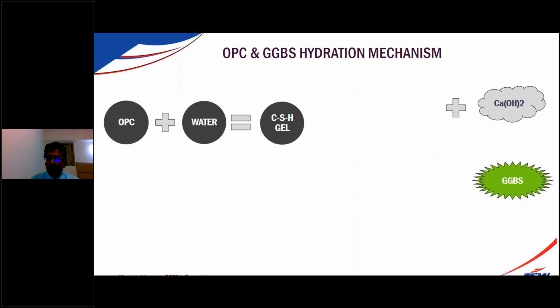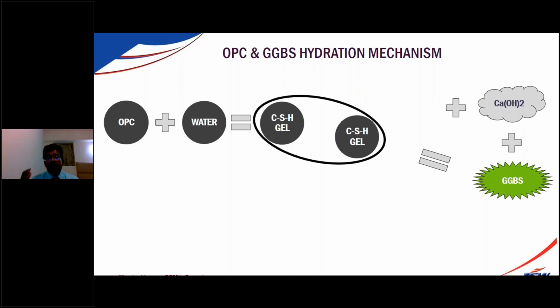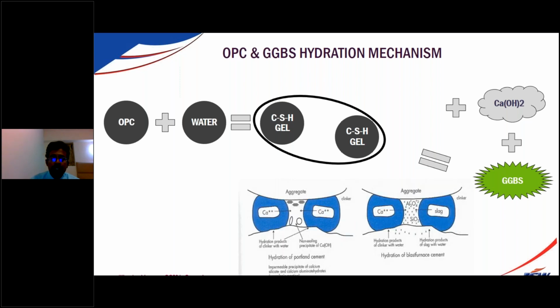How can that be done? By GGBS. GGBS has higher calcium oxide content, CaO, up to 40%, and it will react both hydraulically and pozzolanically with calcium hydroxide to convert it into a durable product, additional CSH gel. That is the advantage of this product. So it is going to have a double reaction. Double reaction means more strength, more durability, more particle packing. These are all the advantages of using GGBS.